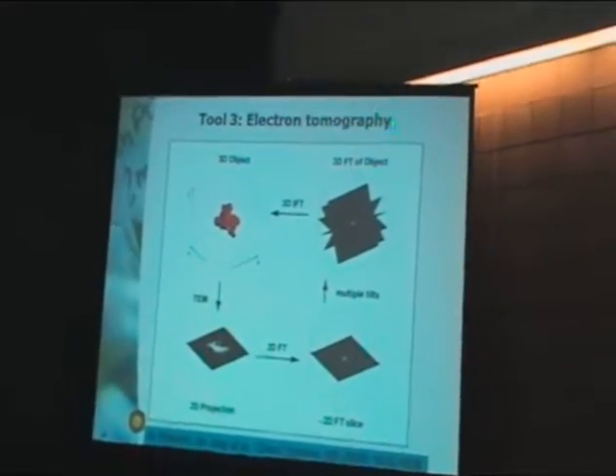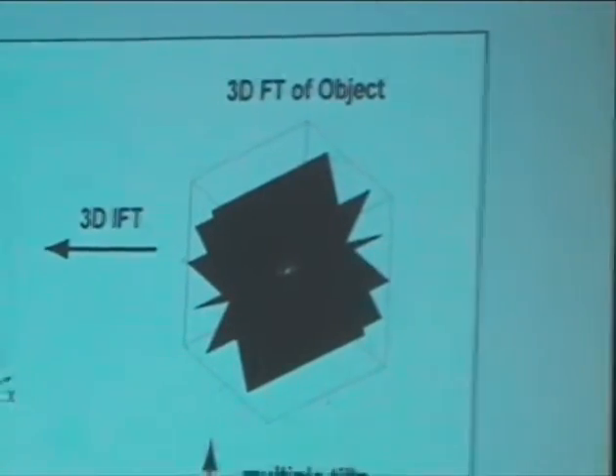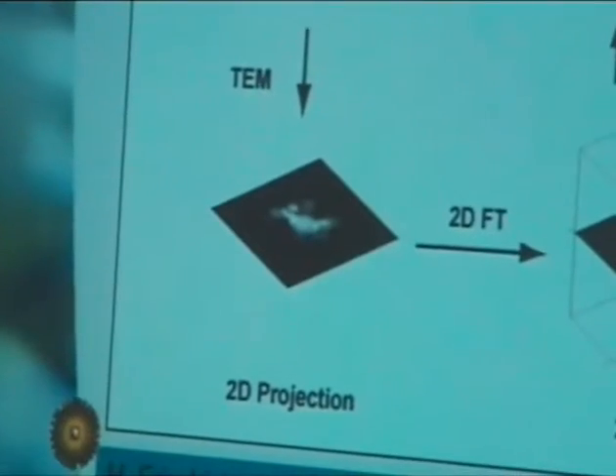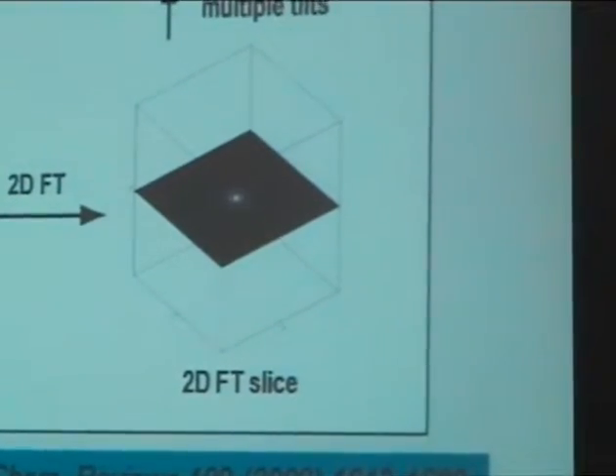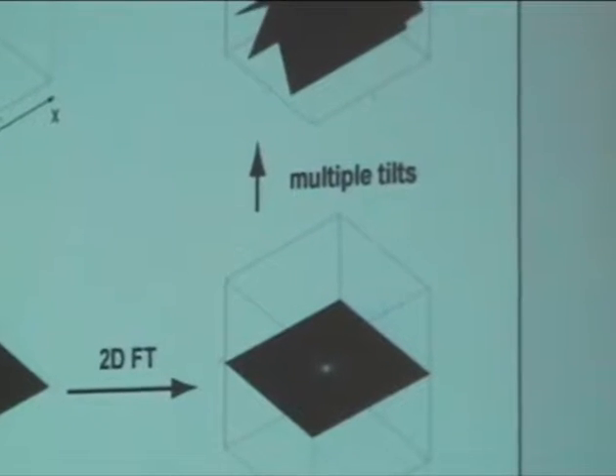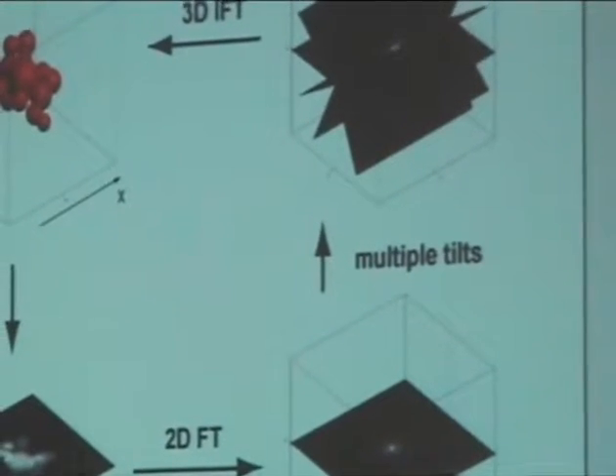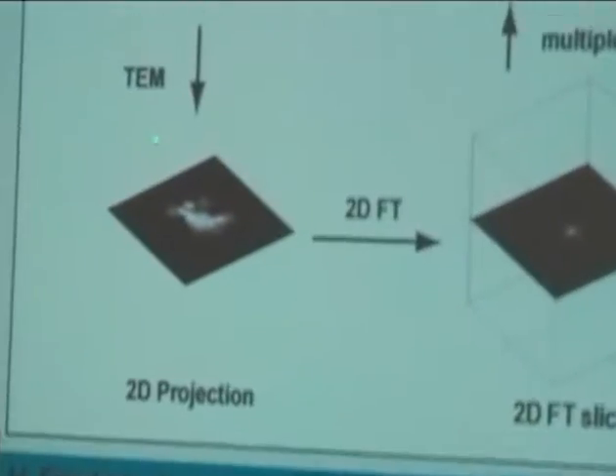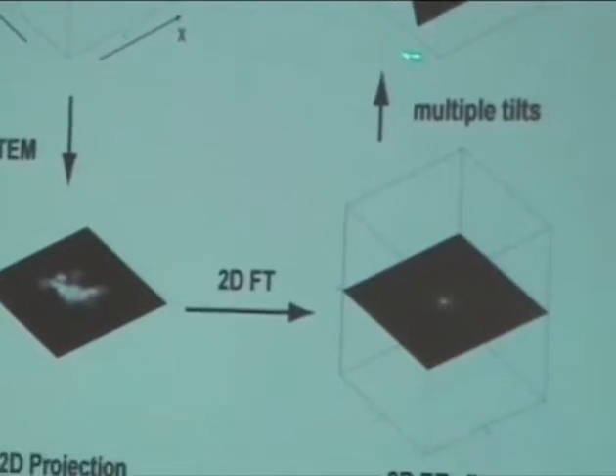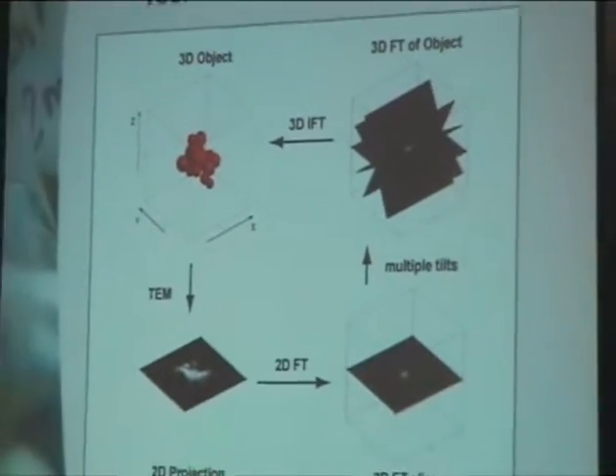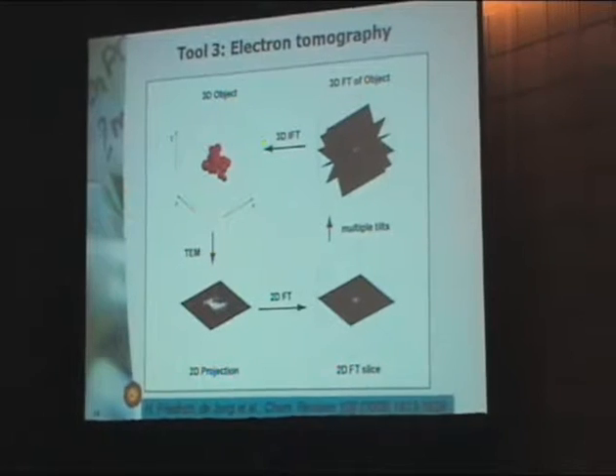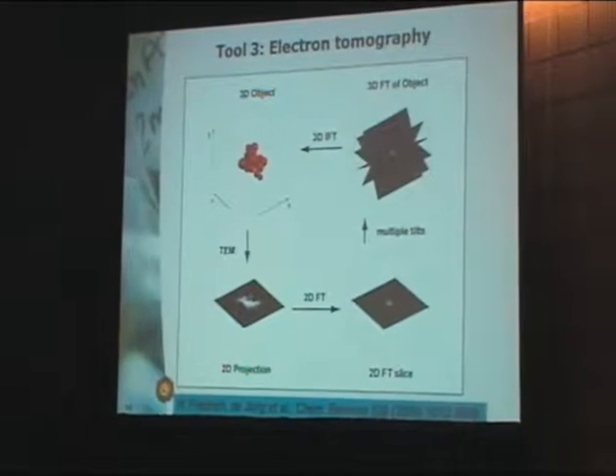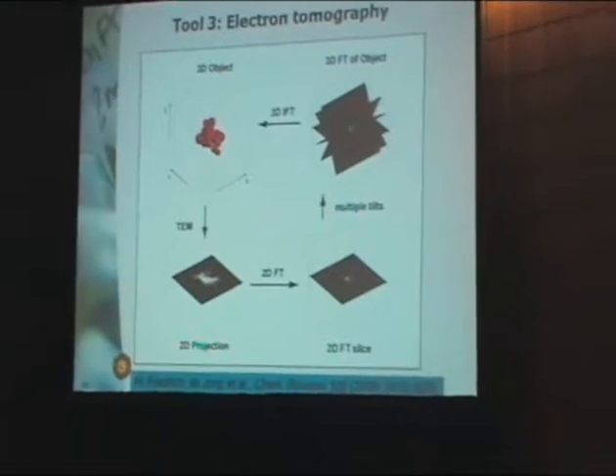Electron tomography is in our toolbox, and again that was introduced this morning. The problem is if you have a cluster of nanoparticles and we have a transmission electron microscope, the electron beam will go through the cluster and we will observe a projection of that cluster, which makes it very difficult to derive quantitative data of particle-particle distances from this projection. So what we do is multiple projections, thereby fill up the, after Fourier transformation, the three-dimensional Fourier space, and inverse Fourier transformation gives us the possibility to numerically calculate the three-dimensional object.